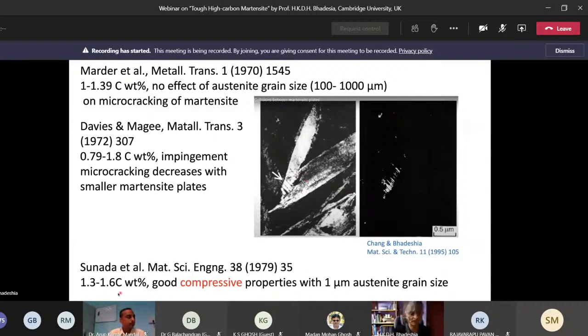And later on, in 1979, there was a paper looking at steels with carbon concentrations up to 1.6 weight%, and they used an incredibly fine austenite grain size, 1 micrometer, and they found, using compressive tests, that the smaller the austenite grain size, the less chance there is of the martensite plates cracking. Although these tests were done in compression, if you compare with a large austenite grain size, even the compression properties are not good. So the basic hypothesis that I want you to take away from this is that if you can reduce the length of martensite plates by refining the austenite grain size, then those plates are less likely to fracture during the actual formation of martensite.